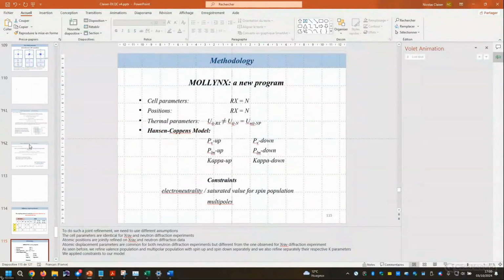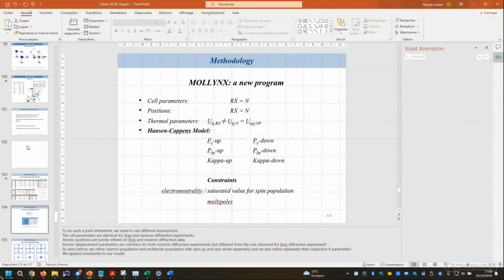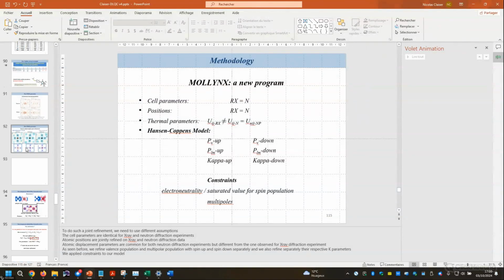Another question on ADPs. Given the different temperatures of the experiments, how well do the ADPs follow the trend expected for harmonic oscillators? It depends. It depends on the system. It's not something you have to take care of already. And I can show you that, for example, for the description of the yttrium titanium oxide, it was not possible to obtain good results if you don't introduce anharmonic thermal parameters.